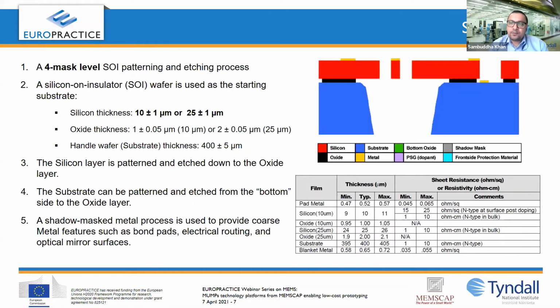So how exactly does the SOI MUMPs process look? It starts with a silicon-on-insulator wafer. It's a 4-mask level SOI patterning and etching process. In the silicon-on-insulator, you can see there are 3 layers. The top one, the red in color, is the device layer or the active layer, where the designer needs to pattern their device. The blue one is the substrate layer, which acts as the substrate, more for anchoring the entire device.